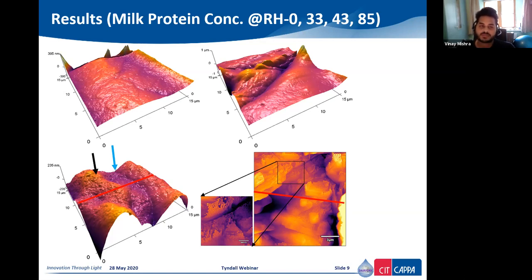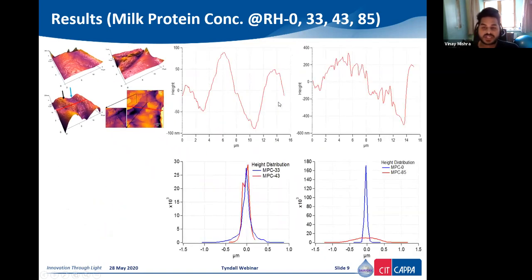There is a primary layer at the top, and there will be a very dense casein structure at the bottom, and they are one of the issues behind the rehydration. They try to stick together. So showing again their orthographic projection, you can see the dimples on the surface of milk protein concentrate started to appear with increased moisture content on the surface. And again, they started to swell with partial rehydration at moisture content of 85.